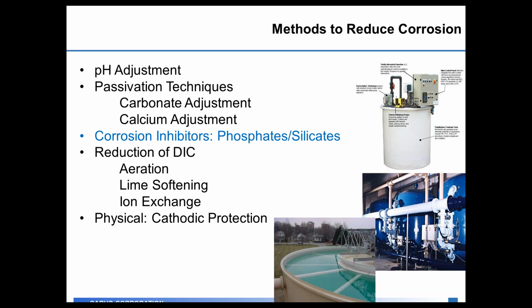There are some other techniques you can take into consideration. One would be a reduction of your DIC, which would be achieved through either aeration of your raw water or through a process like lime softening or ion exchange before you send the water out the door. Finally, you can do some physical protection of tanks and piping out in your distribution system. This type of corrosion protection would only protect that piece of equipment, but where you would see these is in water towers and water tanks, where they use either electrodes to protect the tank or coatings to protect the tank from corrosion issues, and that's to protect one part of the distribution system.